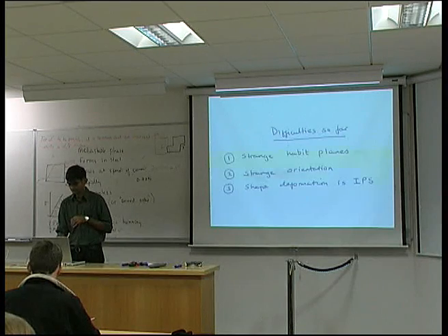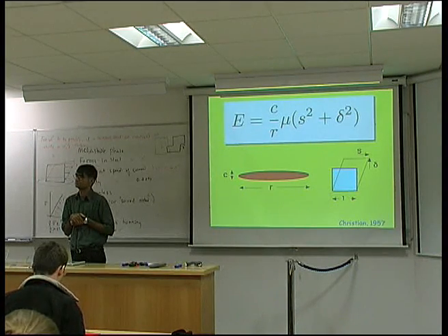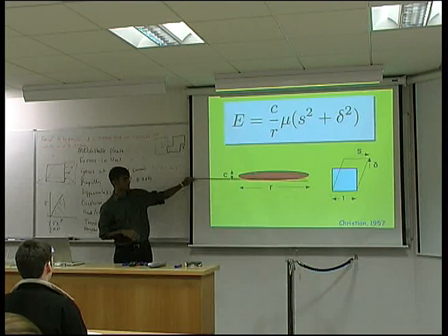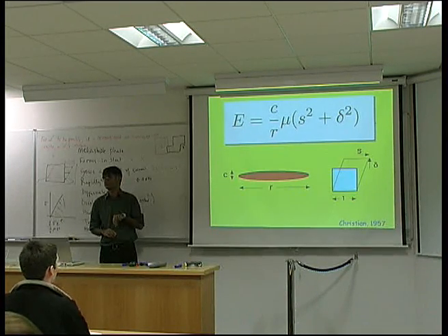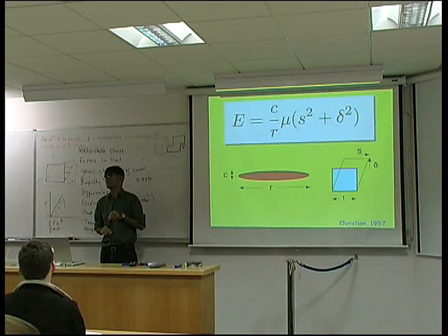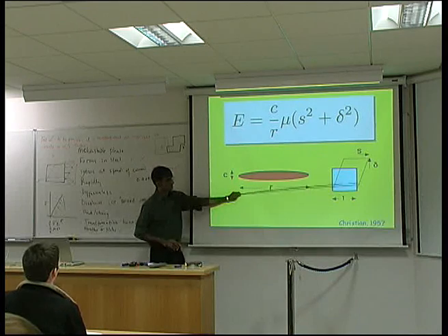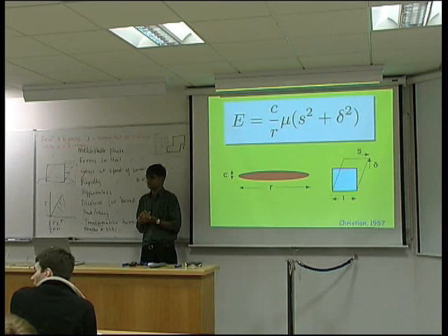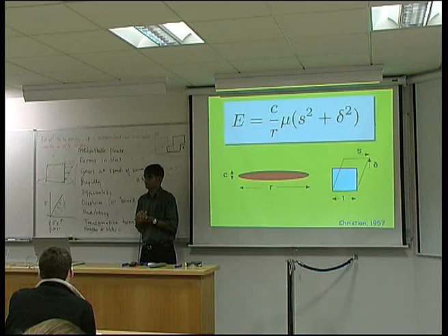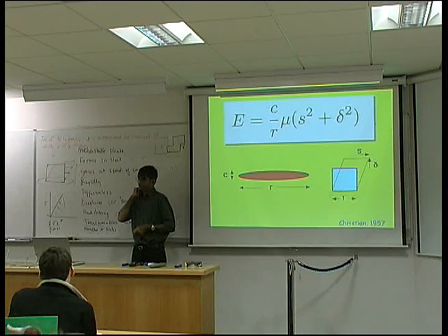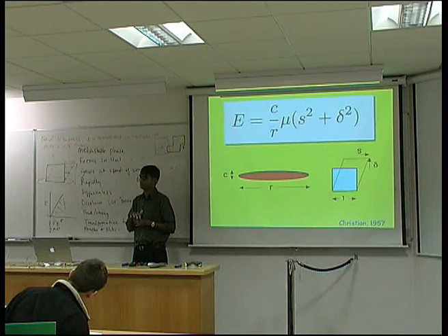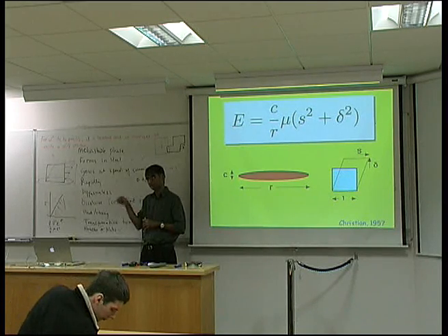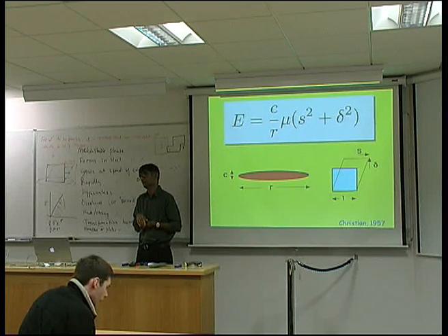Yeah? On the previous slide, you've shown me the martensite plate. Yeah, it's the average plane, yeah. But is the orientation of that related to the square that you've drawn there? Both have to be included in the formula, that has to be correct. How is that then irrational and complete? How can you not tell what the habit plane is going to be when you have an invariant line in the figure? That's right. It has to be included in the original crystal. But then the habit plane is related to the invariant line. Yeah, it must contain the invariant line. And yet it's irrational. Yes, exactly right.